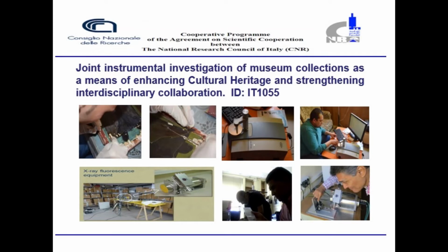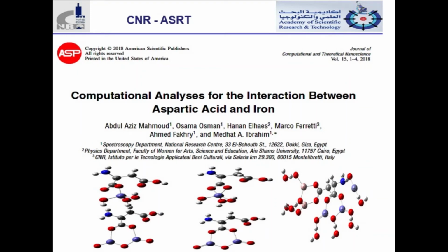Based on the experimental analysis, we assigned some interaction between layers. For example, to describe what is going on in the Coptic icons, we propose two layers. In this work, which was published with our colleague Marco Ferretti, we found that some metal oxides interact with amino acids, for example, and in the presence of water molecules, the total dipole moment is increased, which increases the reactivity and could be a reason why the Coptic icons, for example, are fragile.